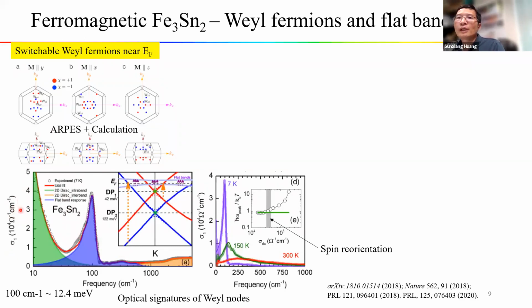So the optical conductivity measurement shows the contribution from the Dirac bands as well as the flat band. It's interesting that it shows the flat band is very close to the Fermi energy. It's only about 10 to 20 milli eV. So further analysis indicates this sharp peak depends on the temperature. This dependence happens in coexistence with the spin reorientation, which happens at about 150K in the bulk single crystals. So they attribute this sharp peak to the Weyl nodes near the Fermi energy, which can be switched by the spin reorientation.